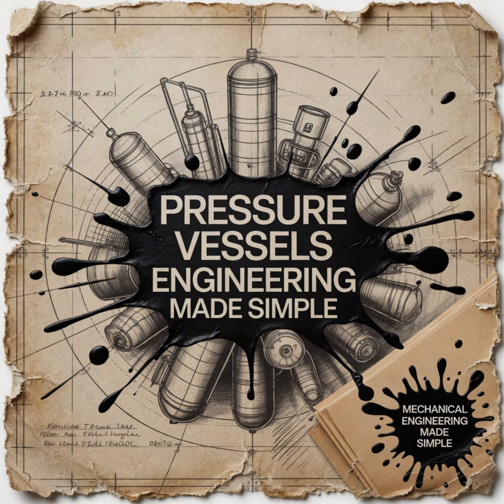The sources also touch on vacuum leak testing, which is a completely different paradigm. Right, for things like power plant surface condensers. Yeah. You aren't testing for bursting strength. You're testing to ensure outside air doesn't leak in and ruin the vacuum. Yes. In those cases, a hydro test won't find a microscopic pinhole leak. So how do you find it? They pull a deep vacuum on the vessel, and then a technician goes around the outside of all the welds with a wand, spraying a fine mist of helium gas.